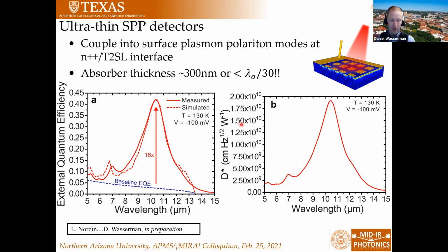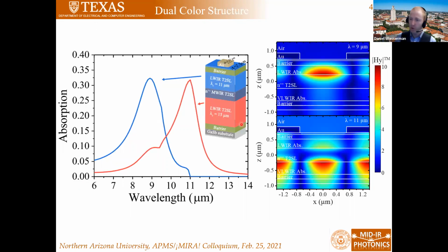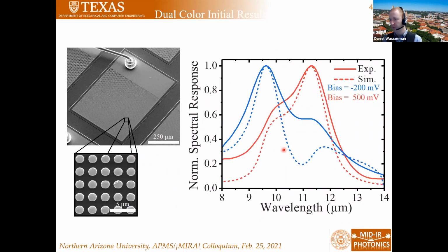So we can actually go nano with our devices. We can even do some even cooler things. This is a device where our plasmonic layer is buried. It's a thin plasmonic layer, and we grow a detector above and a detector below our plasmonic layer. So we're leveraging a different type of plasmonic mode. These are called long-range surface plasmon polaritons, and you can see that we can get a mode that is either on the top interface or one that's on the bottom interface. When we apply bias, we essentially shift between these two detectors, and effectively we can design a detector that controls the wavelength at which it absorbs simply by flipping the bias, whether we're collecting from the bottom or the top detector. We fabricated this as well, and these are just preliminary results, but you can see that we do get a fairly nice switching depending on whether we're operating in reverse or forward bias.